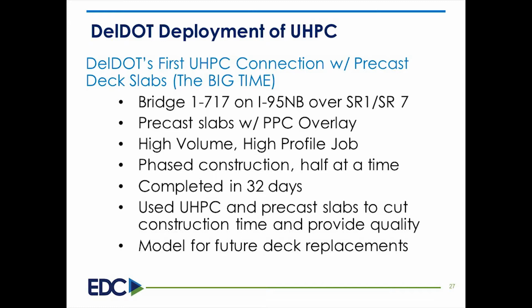And we had precast slabs with a PPC overlay on top of it. And we chose to use an overlay, it's like a 3/4 inch overlay, in case we had any differences in the slabs. But very high volume, very high profile job with phase construction half at a time.